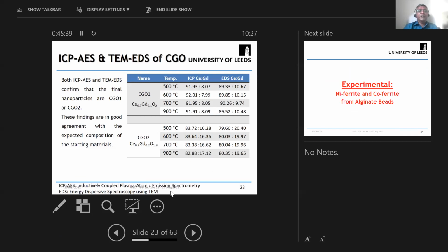So this was the nominal concentration of cerium and gadolinium in the nitrate solution that we used for the ion exchange process. And we did the ICP analysis and EDS using the TEM particles. So we did EDS under TEM, not under SEM, because with SEM you won't be able to see the particles at all. These are tiny particles. So we then decided to do the ICP analysis and EDS analysis to confirm the cerium to gadolinium ratio.